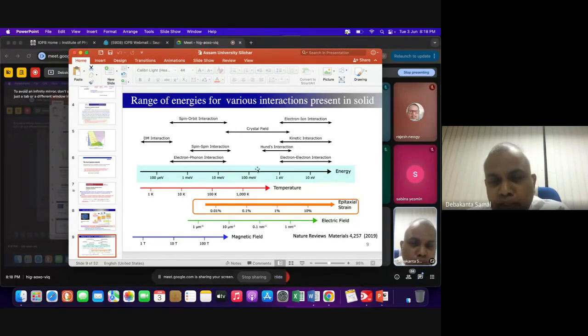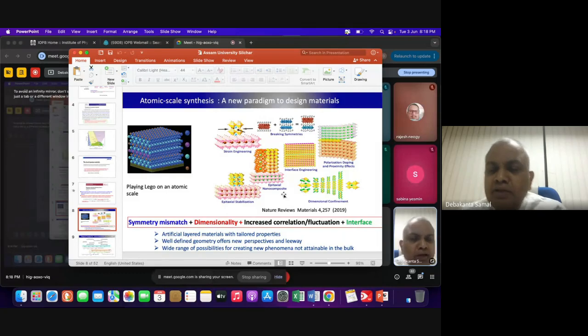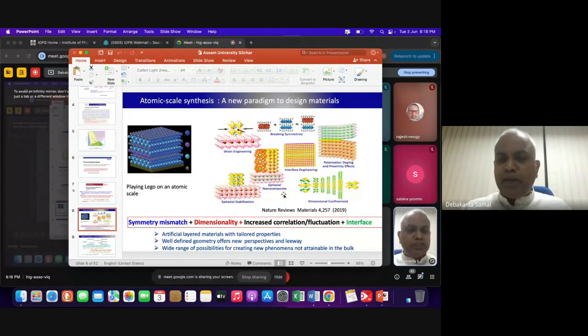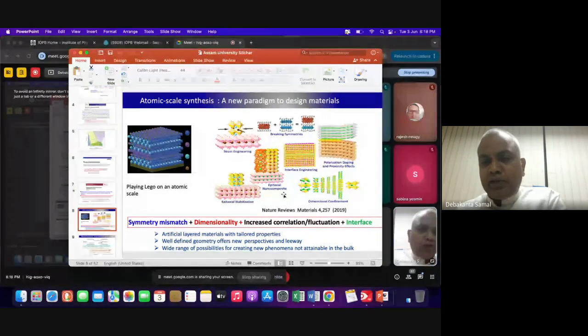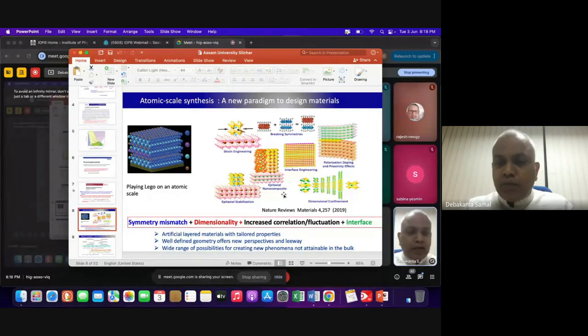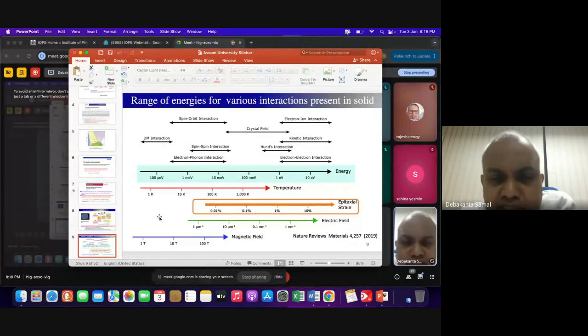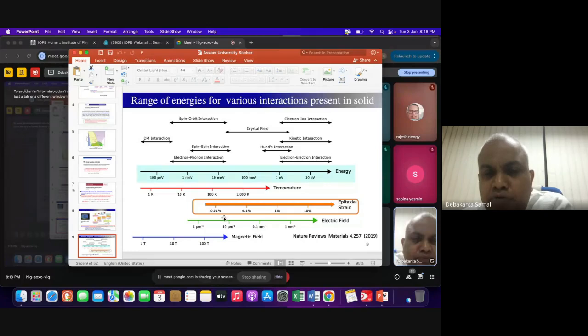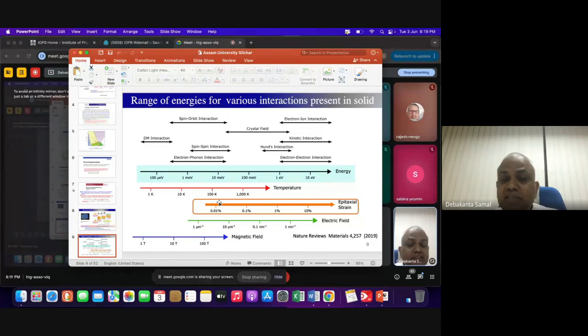And if you look at their values, this is your energy, which I put in milli-electron volts, and this is your temperature. I was talking about strain. When you grow one material on top of another, they can get strained because you are growing a material whose lattice parameter is different. You are putting one atomic layer on another atomic layer, and because their lattice parameters are different, the atomic layer will get strained as it tries to follow the underlying layer. So if you look at the number, just by making 0.01% of strain, you should understand that 0.01% of strain is equivalent to 100 Kelvin. That means by straining the material a little bit, the energy that you are gaining or reducing, depending on the context, is of the order of 100 K.